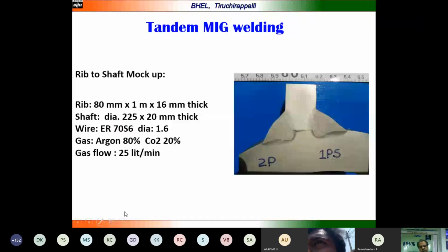Macro of the weld we made with the shaft and the rib. Shaft diameter is 225 mm, the rib is 80 mm by 1 meter and 16 mm thick. This welding can be done very easily by using this process, using argon 80%, CO2 20%, gas flow 25 liters per minute. ER70S6 is used for the carbon steel and the welding has been done successfully. You can see the fusion level and everything is meeting the requirements. There is no lack of fusion or anything else.